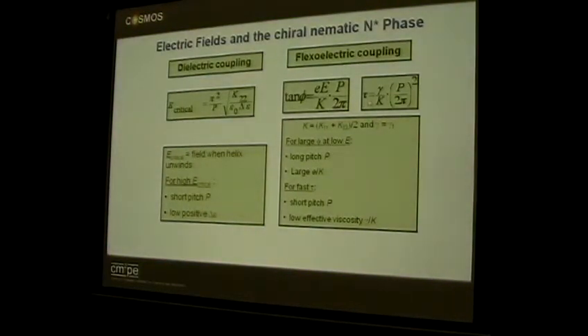Okay, so the response time depends on something like a twist viscosity, an elastic constant, and the pitch of the system. So, if you want a fast device, you make the pitch very small.